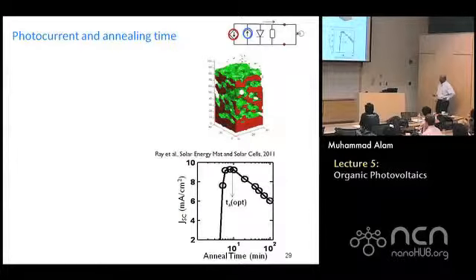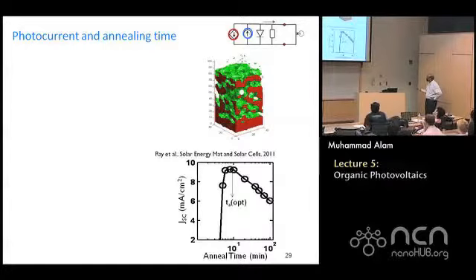Now, the trick is the following: if you really look at the short circuit current that is coming out of the cell, out of a complex cell, that really doesn't go from a high value to a low value. Rather, it starts with 0. Now you wonder, why would it start with 0? And then it goes up, goes through a peak, and this is why the chemists and engineers who do not care about theory stop by using a lot of grad students. This can be empirically found.